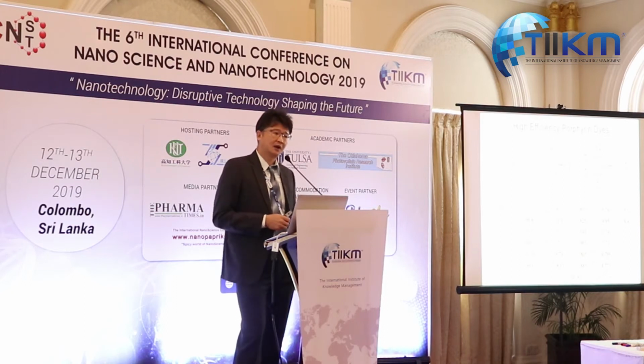In 2011, YD2-o-C8 set a new record. Our porphyrin GY50, with the benzothiadiazole inserted between phenylene and acetylene, achieves an efficiency of 12.75%, which is even better than YD2-o-C8. In contrast, GY21, with the carboxy group directly attached to benzothiadiazole, shows much lower photocurrent and photovoltage because of much faster charge recombination as compared to GY50.